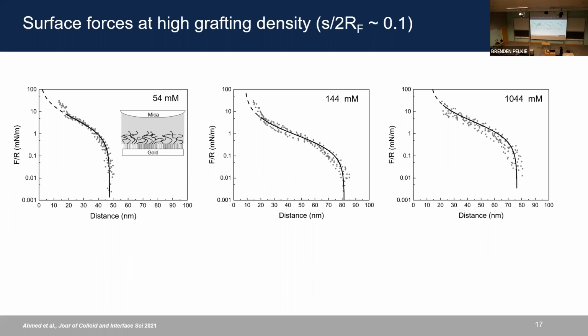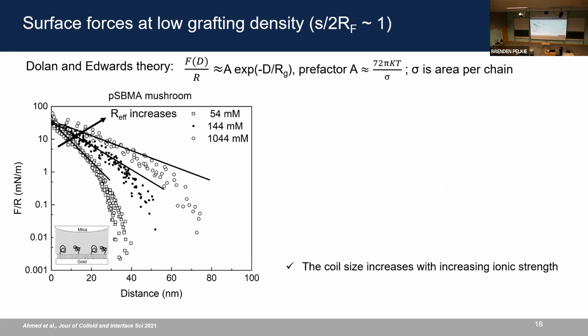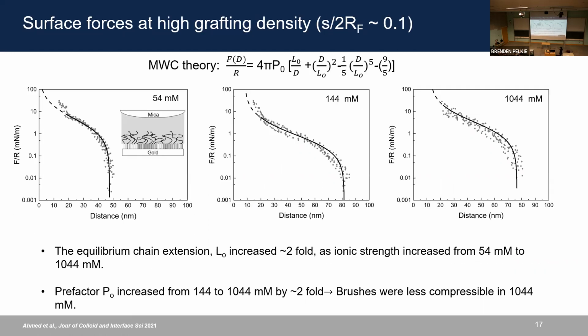And in order to compare these three force distance curves quantitatively, we fitted the force distance profiles to Milner-Witten-Cates theory, which describes the interaction force as a function of chain extension and distance. We also fitted the prefactor, which scales with the surface force. We showed that the chain extension increased twofold as we go from 54 to 1044 millimolar, as well as